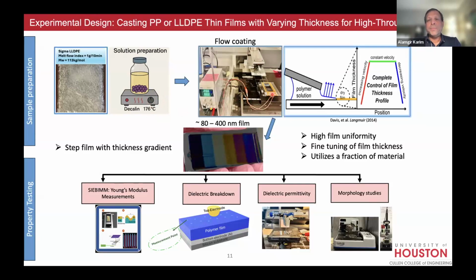We have to improvise. We have to have a substrate that is heated, because you don't want it to cool right away. It should cool down slowly. The solvent should evaporate slowly for uniform film thickness. We have this thing called a flow coater. By changing the speed of drag of the polymer solution with this blade, we are able to create films with a step gradient in film thickness, as you can see from 80 to 400, just by changing the speed in steps.